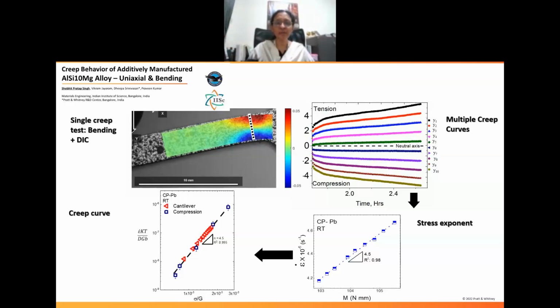Here with one bending cantilever beam that is so small in dimension, 2 millimeters, you can even go up to 500 microns. We are able to get multiple creep curves across this cross section. That is what I'm showing you here. And as a function of bending moment, you can generate the entire stress exponent, etc., and find the mechanism of creep in this, and use this both as a quality control tool in the build plate, location specific, as well as a function of section thickness at various temperatures. So we are working on this and recently published a couple of papers on this.